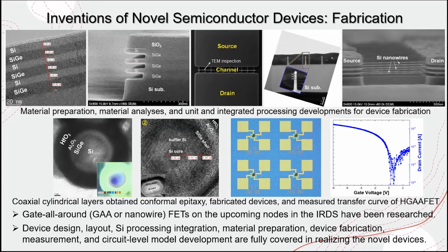So it showed successful IV characteristics, as we can see in the left lower figure. Because this is a PMOS, the current shows an increase in the left outward direction. The center shows the microscopic view of the fabricated devices, and the other shows the TEM, transmission electron microscopy, images taken while doing the fabrication.